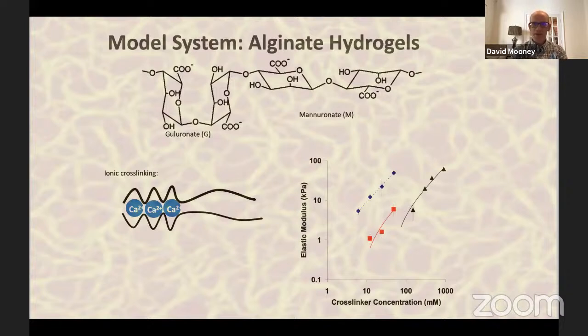Now, the system allows one to very easily and safely encapsulate cells simply by adding divalent cations to a solution. The cells become trapped in a three-dimensional matrix, and we can vary the stiffness of the substrate with the usual tools of polymer science, controlling the polymer molecular weight, the cross-linking concentration, or the composition of the polymer, the M to G ratio. As you can see here, we can get families of hydrogels in which we can very readily manipulate the stiffness as indicated here by the elastic modulus.